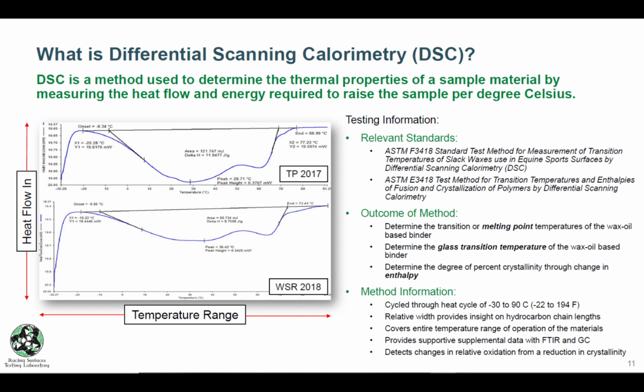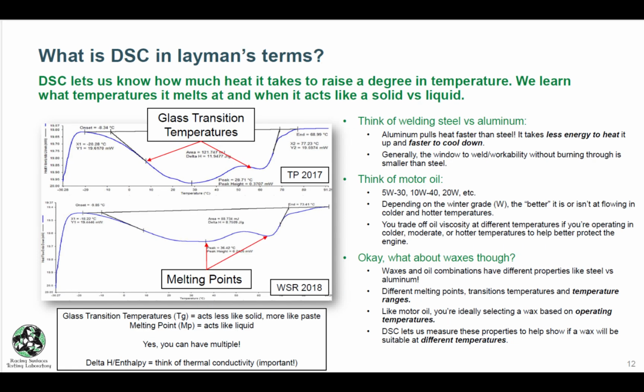And this is actually how you determine what the melting point of the wax is. You use a method like DSC, and this is where you can definitively say this is the temperature at which the wax melts. But we also learned two other important variables called the glass transition temperature. This is the temperature at which we start seeing the wax act less like a paste or a solid and more like a liquid. And there's this degree of crystallinity or enthalpy, and I will touch back on that shortly. But for now, I just want us to focus on the melting point and the glass transition temperatures.